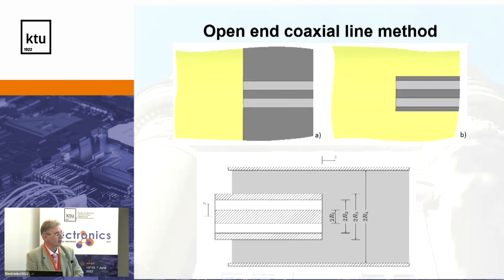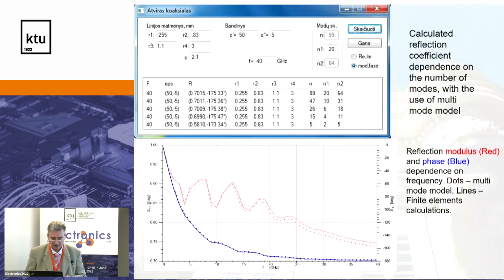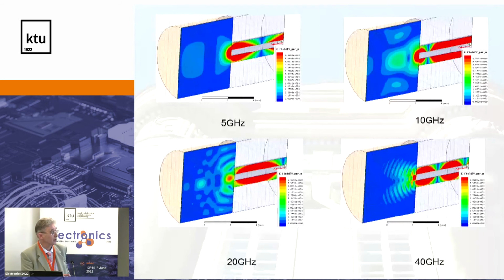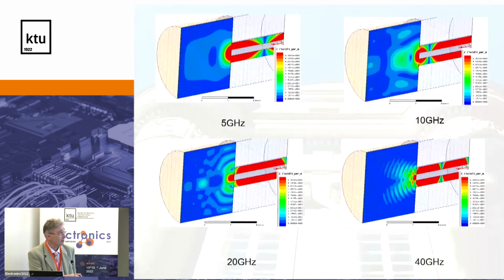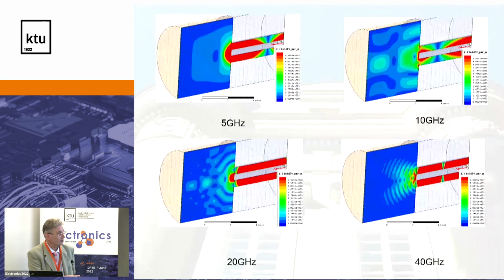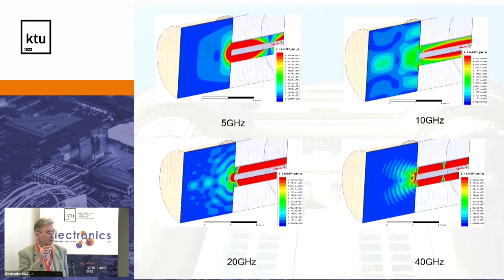Another is the open-end coaxial line method, where a very interesting task: Agilent, or now Keysight Technologies, they produce a probe for liquids, but the method which they are selling does not account for the boundary conditions of the liquid. So you need to have a huge quantity of liquids. But in science, usually you sometimes have samples in very small quantities. So again, we used the same method, again numerical simulations, and we see again that if we have a very limited volume, we have different modes, different vibrations of electromagnetic field which are generated inside the probe.